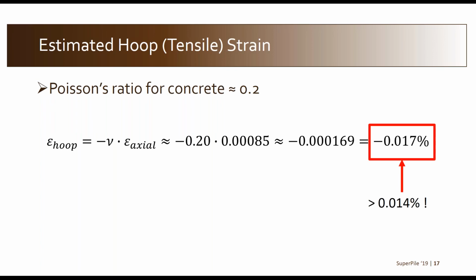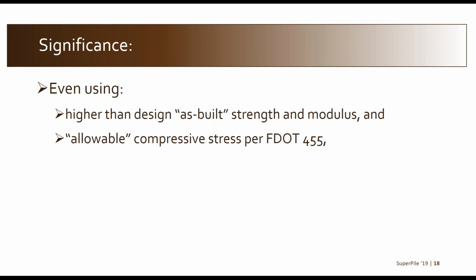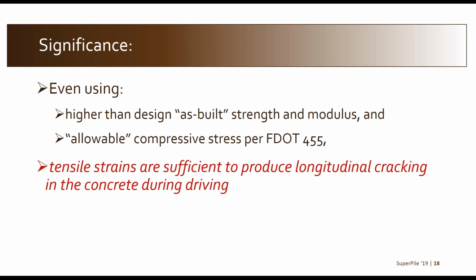which you'll recall exceeds the value at which we would estimate that cracking would occur of 0.014%. So that is significant because that says that even when we take into account the as-built strength is higher than what it said on paper, and knowing that the driving stresses were below the allowable compressive stresses per the FDOT spec, mathematically we compute that the tensile strain is enough to cause cracking because the strain in the hoop direction would cause cracking of these piles. So again, I'll repeat, you're installing this in accordance with the spec, and yet we're basically calculating that it should be cracking. So this is undesirable.